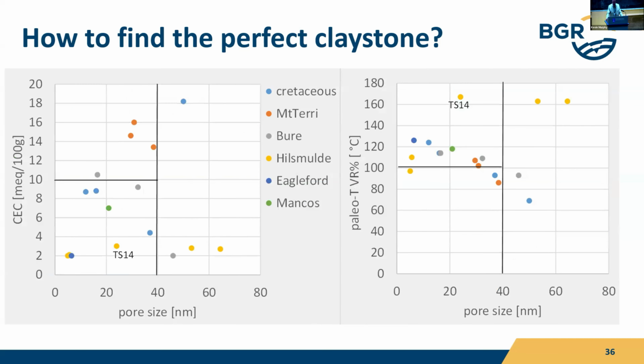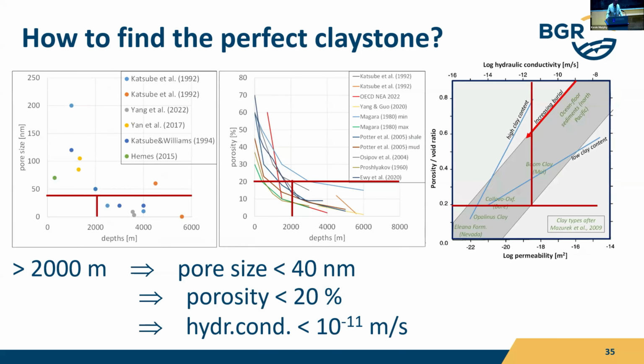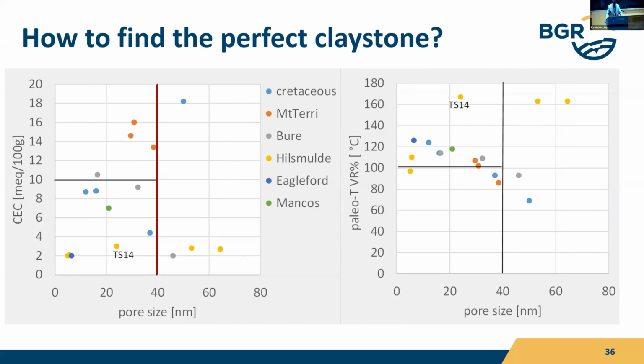So based on this data, we can use these plots. For example, I used the pore size, as I explained before. That is a quite neutral parameter, where this depth can be fixed, but it translates, going back, to this 2000 meter, right? So on the x-axis, these red lines I have, they represent more or less the 2000 meter, okay? So everything which is on the left side is below 2000 meter in this graph, and everything which is on the right side is higher than 2000 meter.